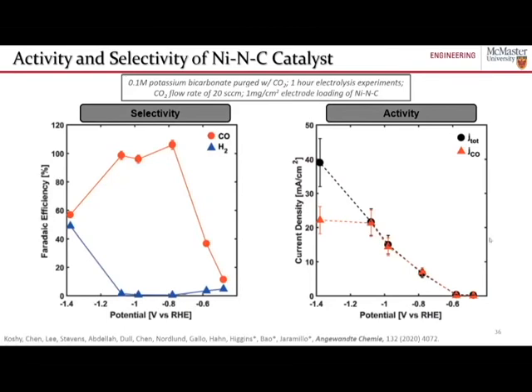And you can see on the right, in terms of the activity, the current densities towards carbon monoxide, we're getting on the order of 10 to 20 milliamps per centimeter squared of carbon monoxide before the formation of carbon monoxide saturates and the selectivity of hydrogen increases at lower electrode potentials. So this is ultimately pretty good. We want to be operating at as high of an electrode potential as possible, so as close to zero as possible. And the fact that at those potentials closer to zero we're forming a lot of CO, we found very, very promising, that this catalyst could be very active and very selective towards carbon monoxide.